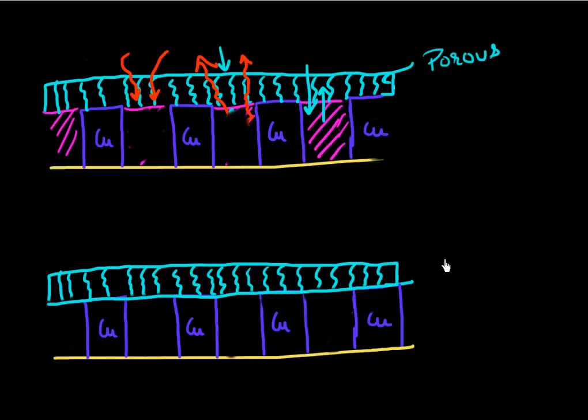The challenges with this approach is that you have to heat it up, so you have to go to higher temperature which might damage your transistor below. Or if you wet etch it, then you can corrode, there's always a chance that you can corrode these metal lines here. But this is a very viable approach of making these interconnects.